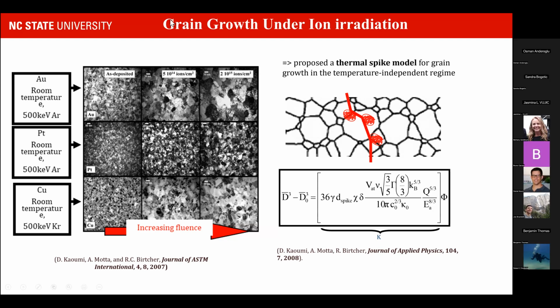And only through additional experiments, we were able to show that only thermal spikes or defect cascades that were happening at the grain boundaries were participating in the grain boundary motion. If you had thermal spikes inside the grain, those defects would recombine very quickly, and the surviving point interstitial vacancies would not necessarily help the process of grain growth, which is driven by the grain boundary migration. And based on this model, we developed an equation for grain growth, which was satisfying in the sense that we were able to capture the exponent of 3 that we saw in the experiment.